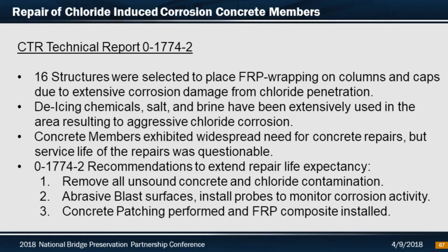So it had resulted in aggressive chloride corrosion, and many of the concrete members had been just completely eaten up with horrible patching. So again, 1774-2 recommended to remove all the unsound concrete, get all the chloride contaminants out, abrasive blast the surfaces, as well as install some probes to monitor future corrosion activity. And then the concrete patching was to be done, and then the FRP was going to be installed.